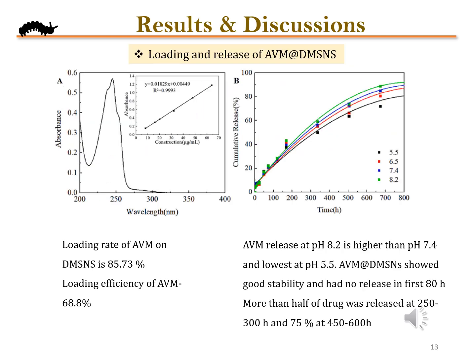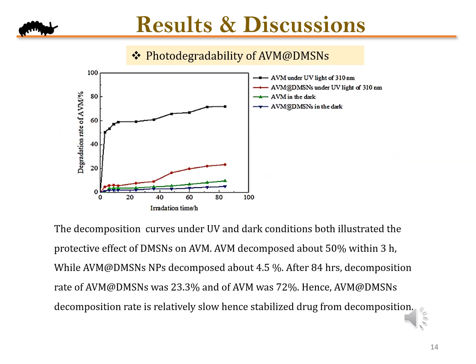Finally, the loading and release of AVM@DMSNs was performed. Loading of DMSNs was calculated to be 85.73, whereas the loading efficiency of the AVM was calculated to be 68.8%. The drug release was calculated in different pH solutions with constant time and temperature parameters at certain intervals of time, and it was found that the maximum drug was released at pH 8.2 than at pH 5.5. Also, the drug showed stability for several hours, which showed that there is a controlled release of the drug.